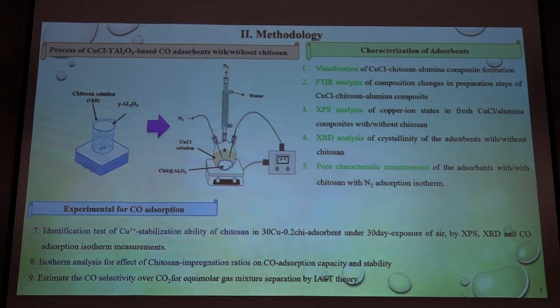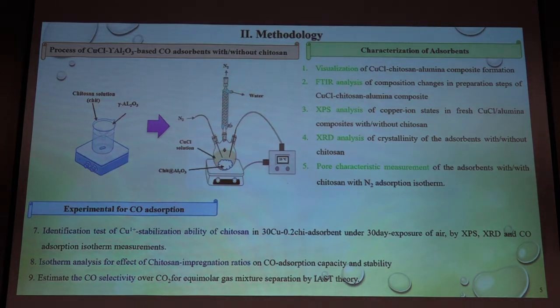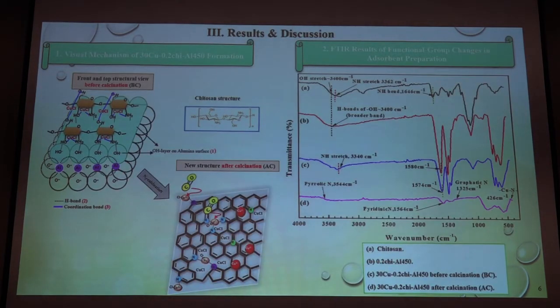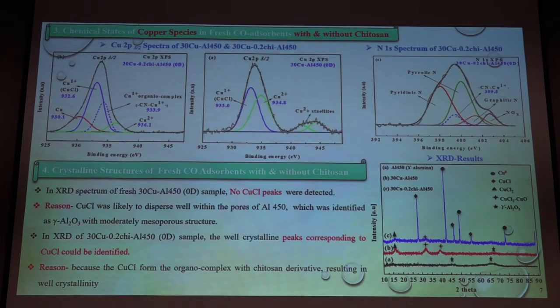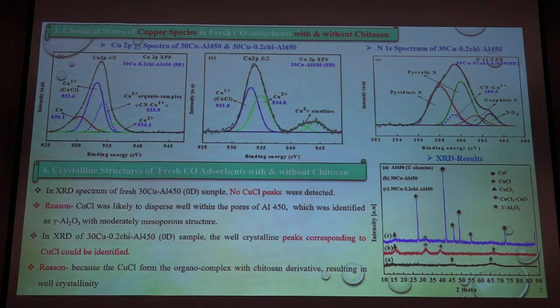So after the preparation, I analyzed these parameters. In the FTIR analysis, after the calcination step, the chitosan's original structure was disrupted, resulting in N-doped carbon on the alumina support, and the nitrogen from the carbon makes a bond with the copper as a complex. That's why I found a copper-nitrogen bond in the FTIR spectrum. Further, I used XPS analysis to analyze the copper ion status in my samples.